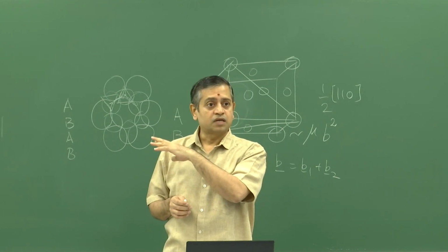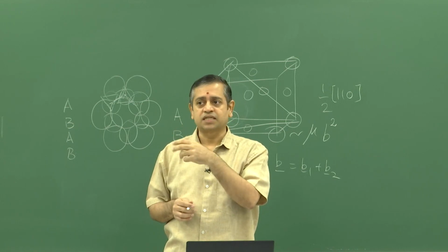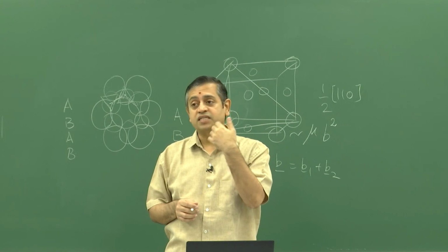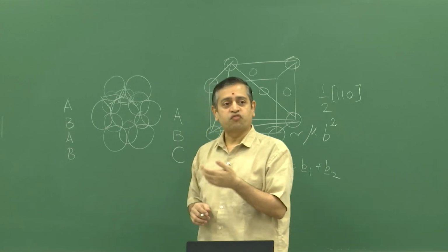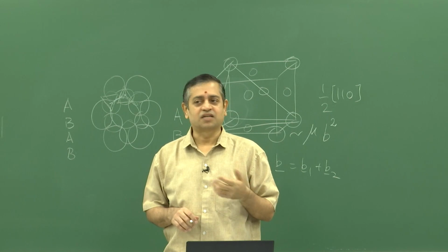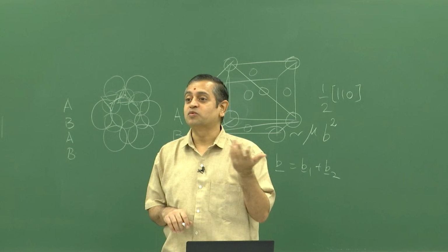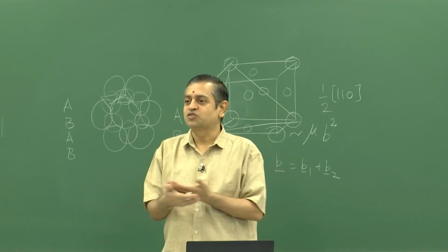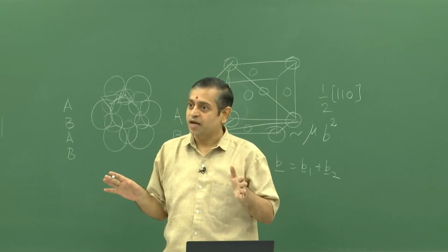This is copper. Silver is a system which is considered a low stacking fault energy material. But the stacking fault energy is so low that the rate at which you form the twins is also the rate at which you can destroy them, or something close enough. So, sometimes even though it has very low stacking fault energy, you do not see so much twinning, because twinning and detwinning happens. This is just partials moving this way and that way. B goes to C and then it goes back to B again. So, that can also happen.